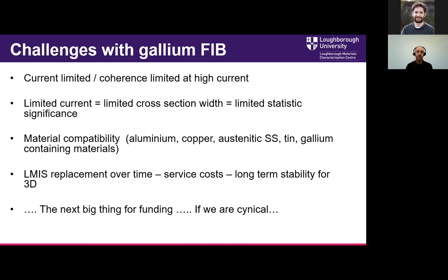So what were these challenges with gallium? There was a limit on the coherence of the sources due to the current limit. And this limits the cross-section width that you can make and limits the statistical significance of some of your results. There were also material compatibility issues, as we've discussed. So things like aluminium, copper, austenitic stainless steel, tin, and gallium-containing materials don't always work the best with gallium.